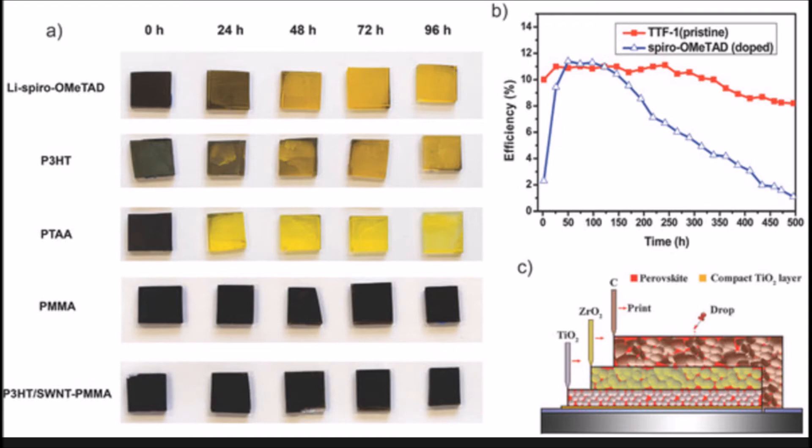In addition, perovskites are somewhat unstable. When exposed to ambient conditions, particularly humidity, perovskites degrade to different crystalline phases or deform different chemical structures. Methyl ammonium lead iodide becomes hydrated when exposed to moderate humidity levels. This causes subsequent breakdown of the crystalline structure which is responsible for the generation of excited electrons.